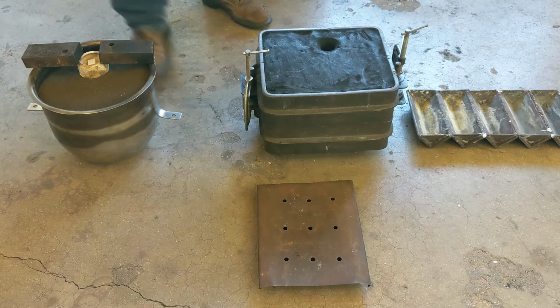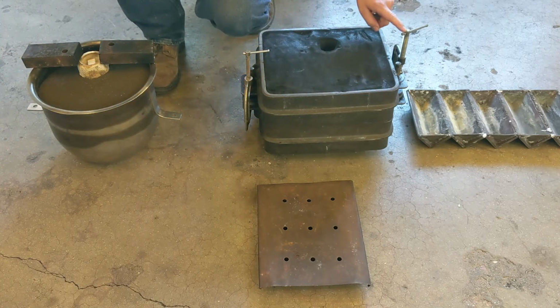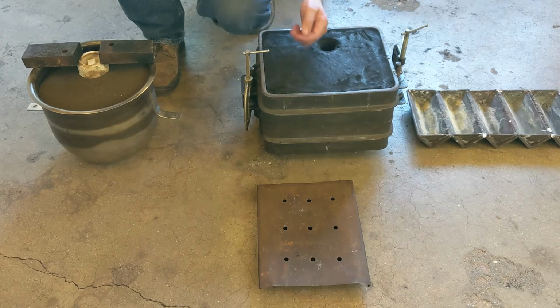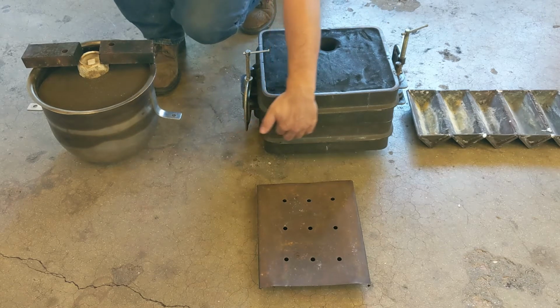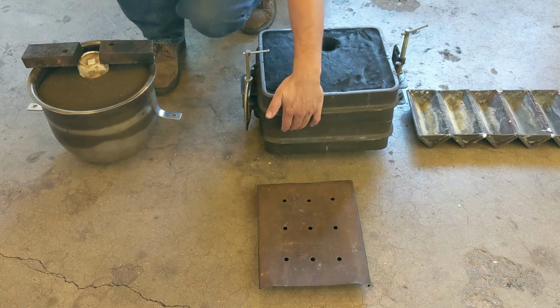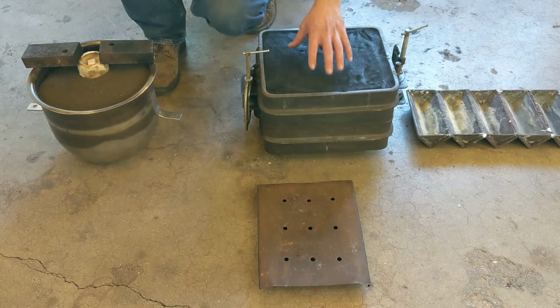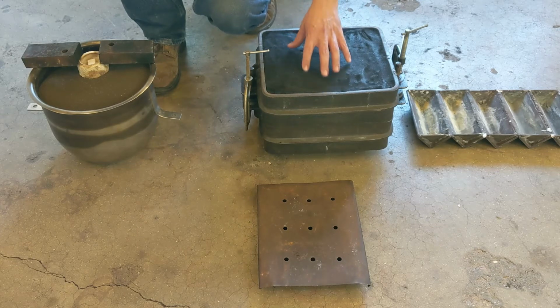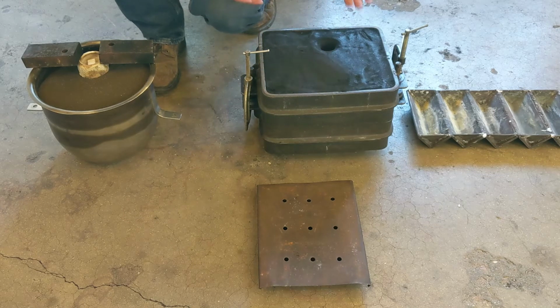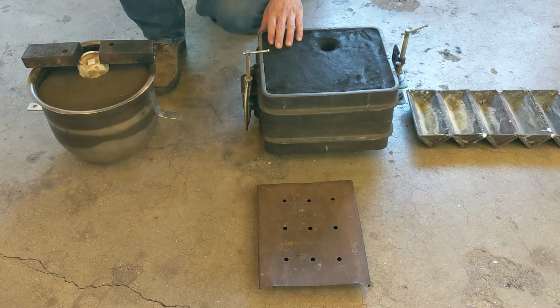And the same thing here, I've clamped the two flask halves of the mold together. The reason for that is, if you think about it, if we filled this mold cavity with metal and the amount of metal above the parting line weighed more than the sand in the cope half, then the cope half would become buoyant and it would lift, and then the metal would jet out of the parting line. That probably wouldn't happen here, but it's a standard safety precaution that we're going to take.